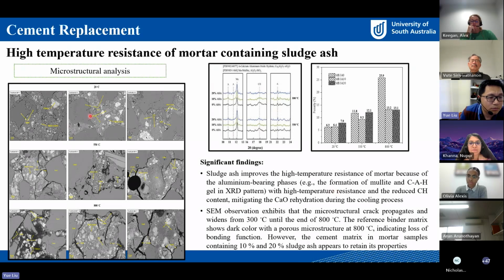This is the SEM observation of some samples after exposure to different temperatures. We can see the reference samples after exposure to 800 degrees show a dark color with a porous microstructure. For the sludge one, the microcracks still progress with the increasing temperature, but the binder matrix still retained its properties. The color doesn't change too much.